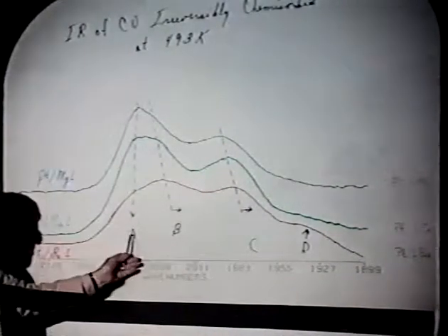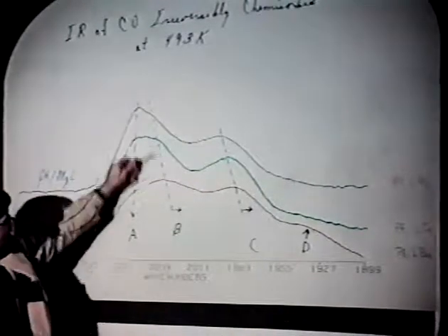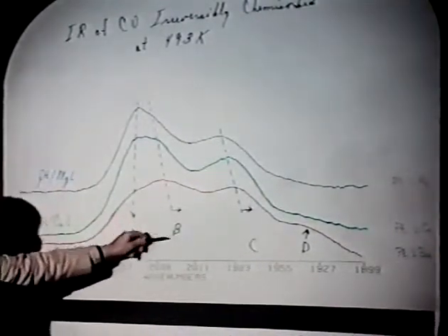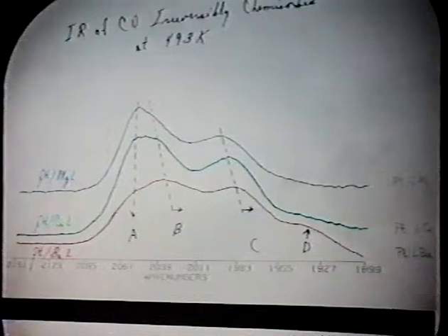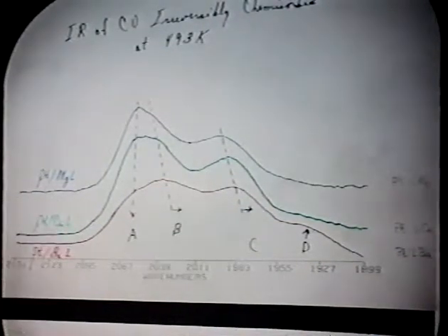Only those potassiums along the main channel are ion exchangeable. And if you then calcine at a high temperature, you move the alkaline earth into these cancrinite cages and put potassium back. So in fact, it has a lot of residual potassium in it. But as you go from the magnesium to the barium, there's not much change in the peak at the highest frequency, but this peak moves to lower frequency, as does this one, and actually a fairly low frequency peak develops on the barium that's not there for the magnesium or calcium. So there's some modest evidence that these are very basic supports.